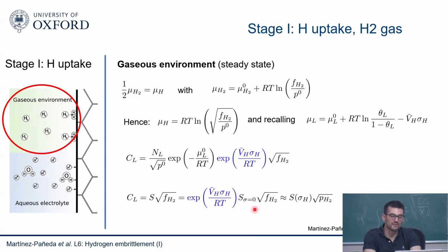There's a solubility term that I'll explain to you in a minute how we measure. There's a solubility term, and then there's this term which is partial molar volume, where we know the gas constant and temperature. But this term is going to be big, so the coupling with mechanics is important, and sometimes chemists don't realize this, and it's quite important. But otherwise, it's a closed form expression. You can see the derivation here.